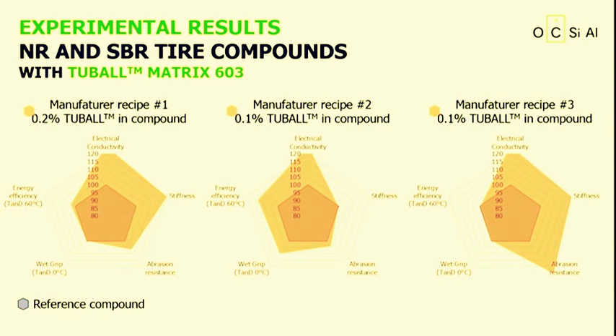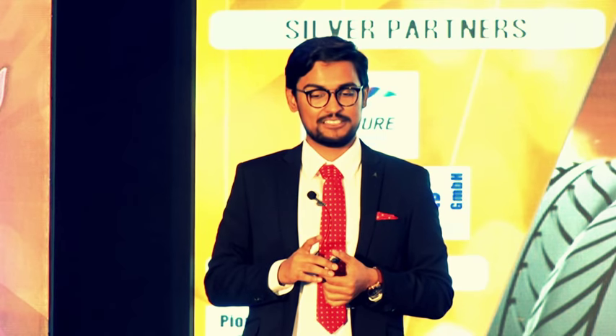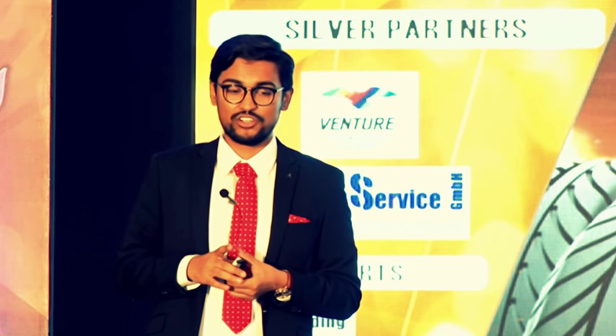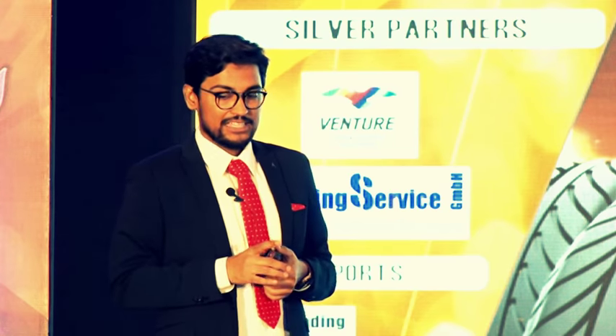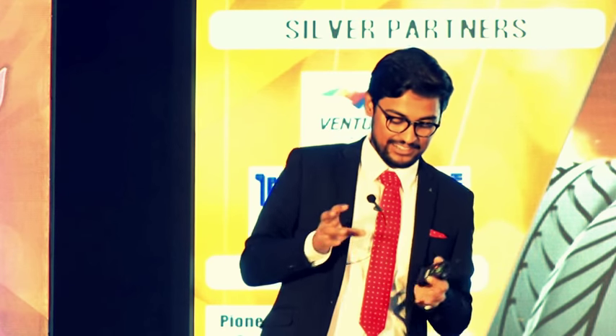Let me carry on. Then NR and SBR tire compounds, these are some other results with 0.2% and 0.1%, and there are 3 recipes. We took 3 recipes, and you would see the increase in results is all over the place. In some compounds, we saw very good abrasion resistance increase. In some compounds, we saw energy efficiency increase, tan delta at 60 degrees Celsius was improved. In some compounds, we saw a good increase in wet grip, in others we did not. There is a reason for that, and that reason could be called the variability of the test because of the orientation of single wall carbon nanotube, or simply to put it, how the carbon nanotubes were compounded.